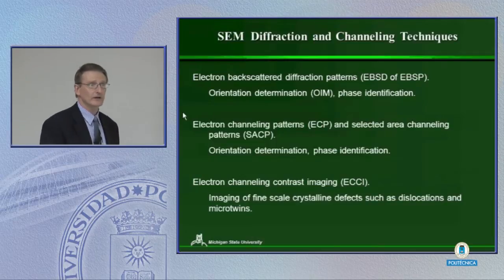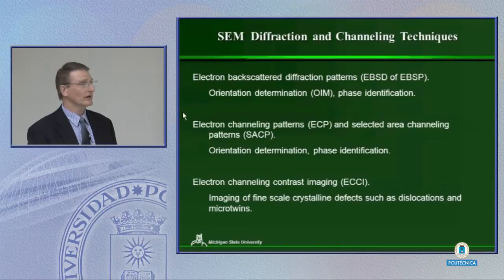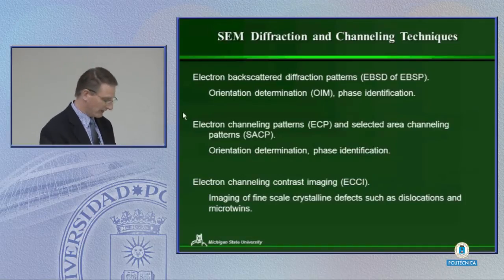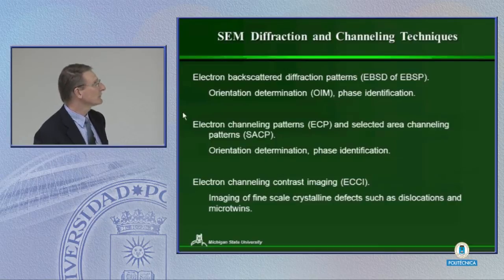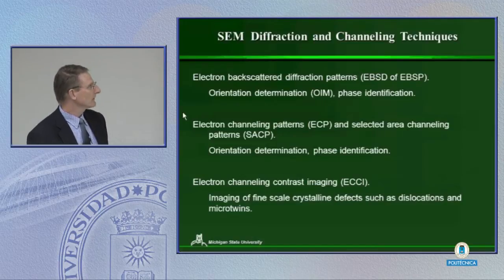We use them very extensively. When I started doing them, it would take 30 minutes to determine one orientation. Now with fully automated systems, we can get 500 orientations a second. So you can just get extreme amounts of data very quickly using it. It's very useful for orientation determination. Has significant but not perfect applications in phase identification.